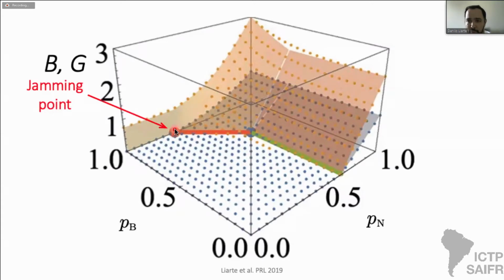So let me explain why we call it jamming. Suppose you build your lattice somewhere in this floppy region here, this X point, and now you randomly add bonds so that you approach the jamming point shown there. As you hit the jamming point, two things are going to happen. The average coordination number Z becomes equal to ZC, which, as I said before, is the isostatic limit of mechanical stability. And the bulk modulus jumps to a finite value. As you continue moving deeper into the rigid phase, the shear modulus continues to grow from 0.